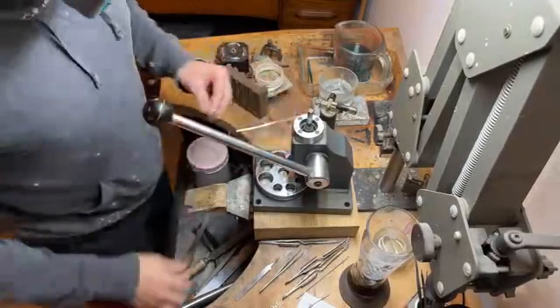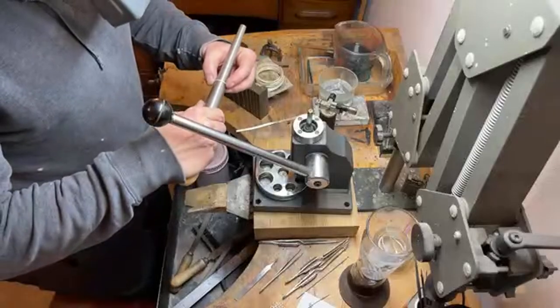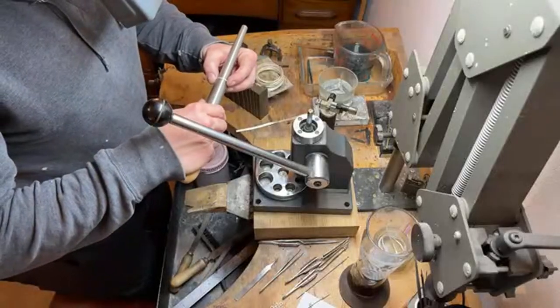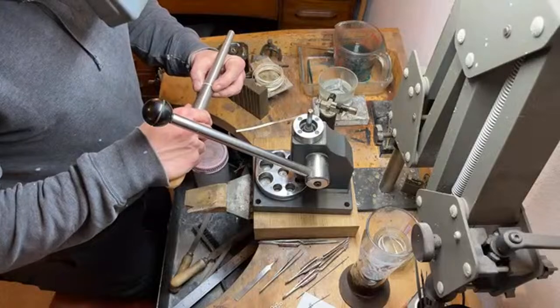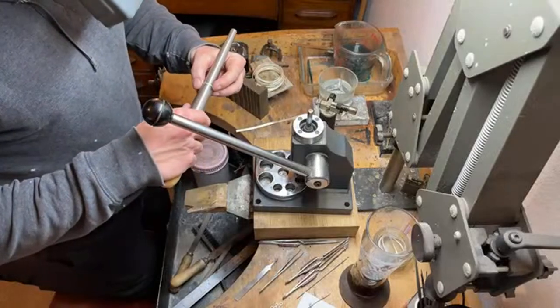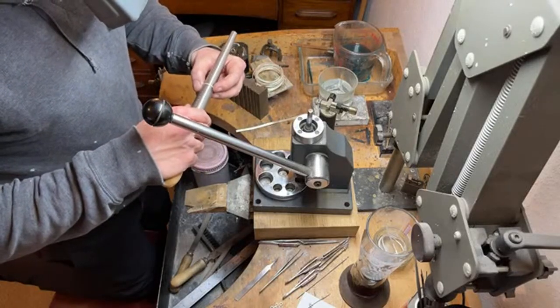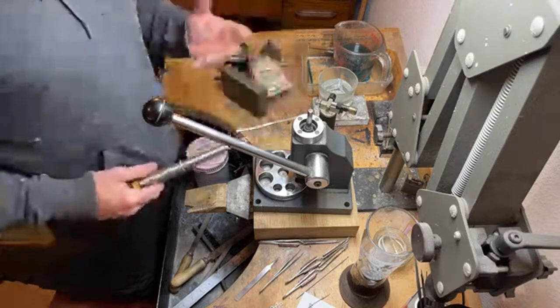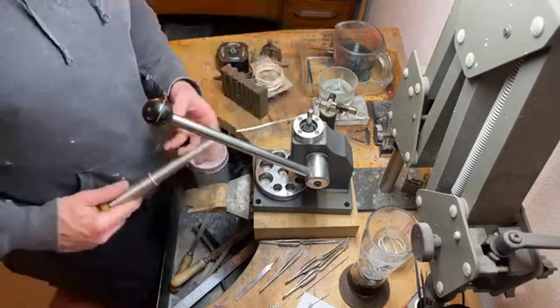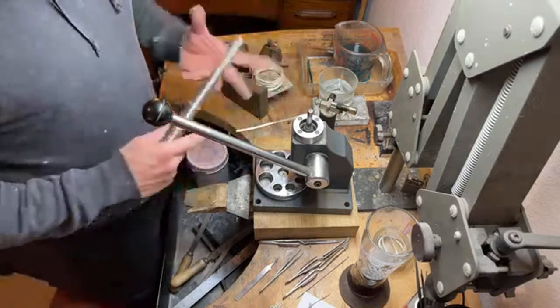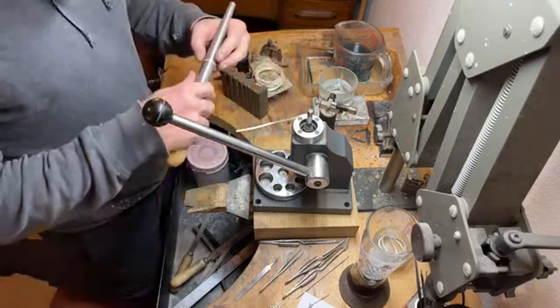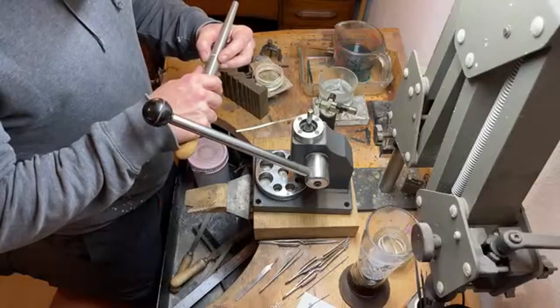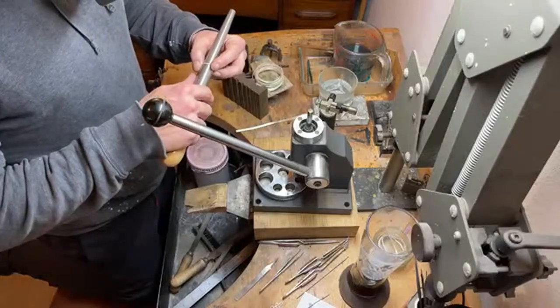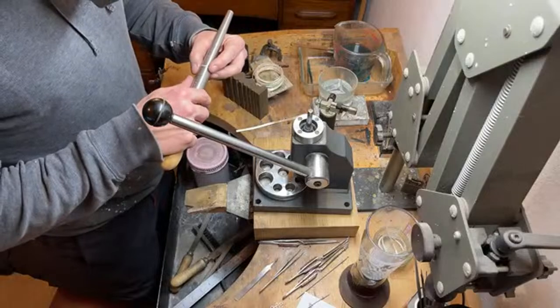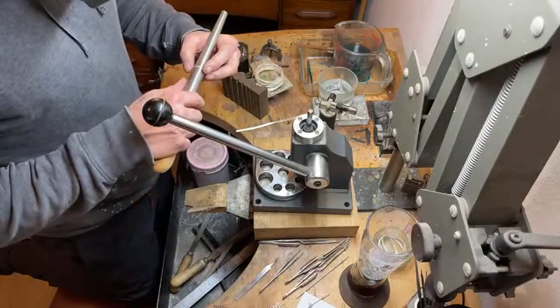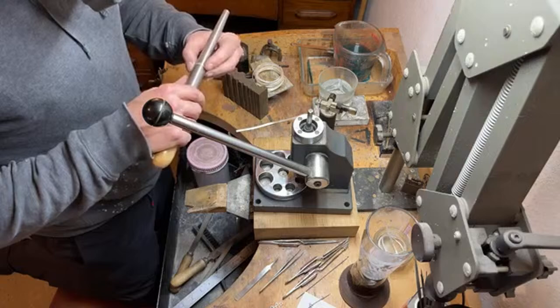to some extent, is you can go to reduce a ring, and because it's tapered, I could look at this freshly made and it'd be W1/2, and then I go to taper it down and it ends up like half a size bigger, which is just from it then becoming perfectly round, but also where the taper's at. You can reduce them and end up with a bigger ring. Vice versa, you could probably do it the other way as well.